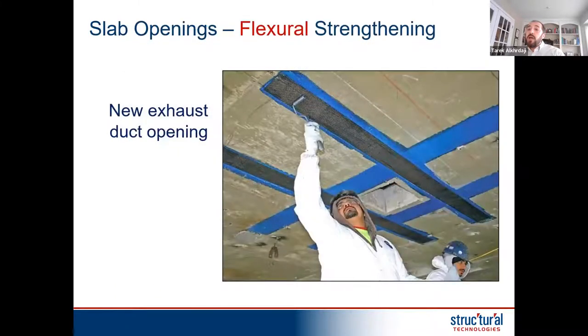We've been using it a lot. I tell you, there's no day that we don't have a project where we're putting FRP around small openings and penetrations, where basically you are cutting a small opening to allow for a duct or a conduit or a pipe through the slab. And by doing this, you're cutting some existing steel. So FRP can be added around the penetration to prevent stress concentration and propagation of, let's say, 45 degree cracks